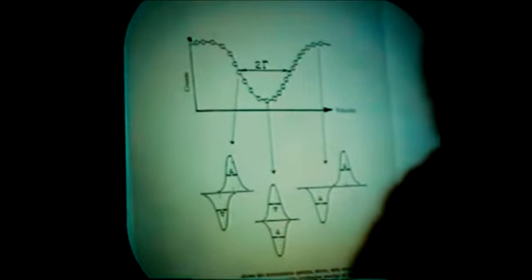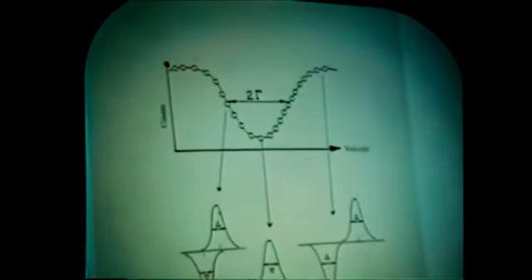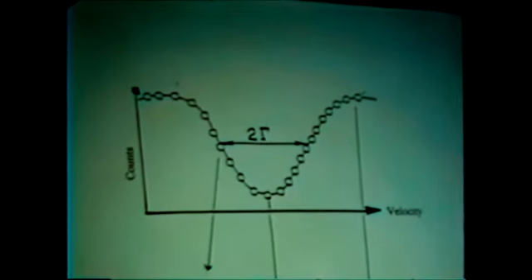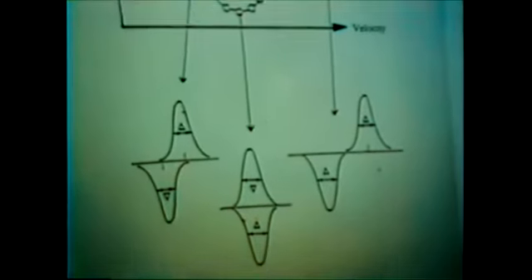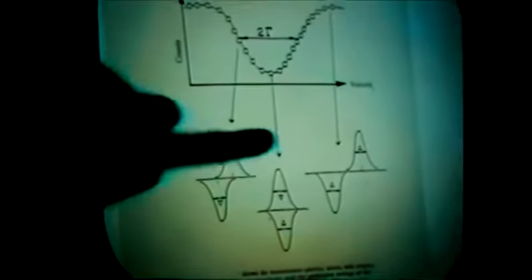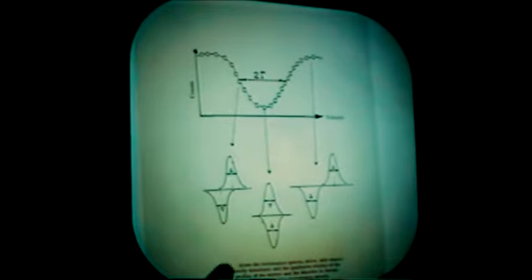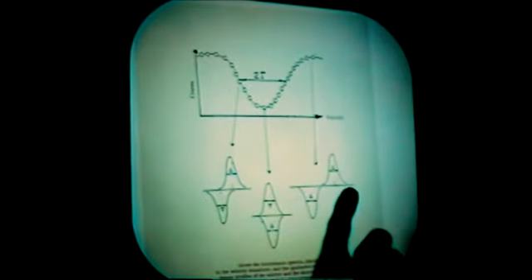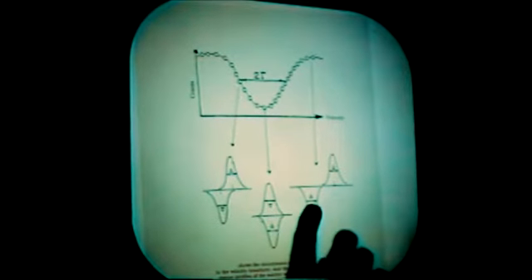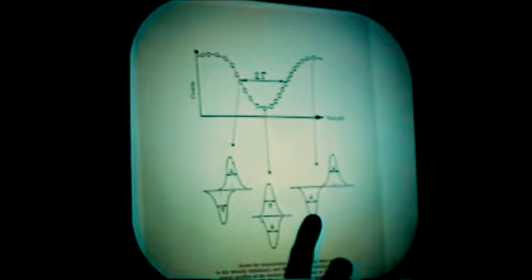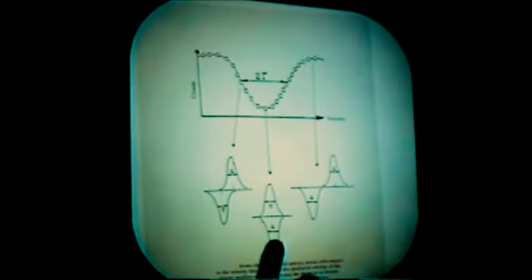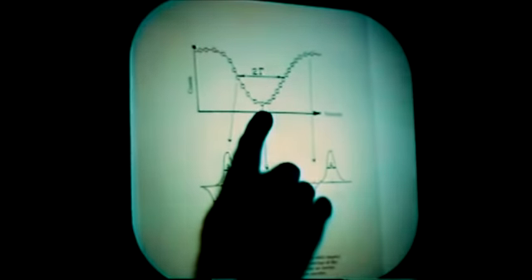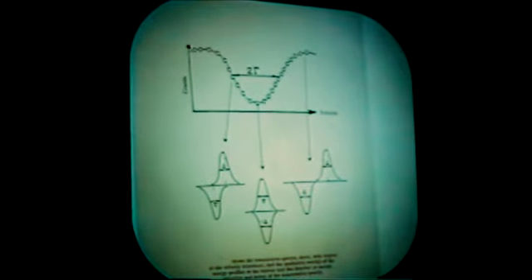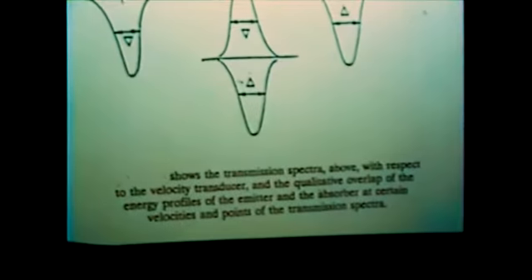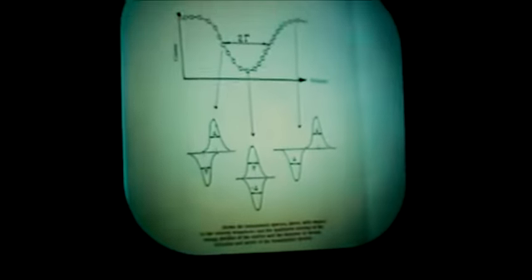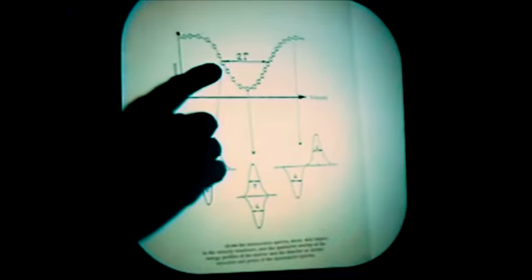Now this is what the transducer does. Let's say this is the energy of the excited state that you're trying to excite. At this velocity, you're moving this in this way, so you have no match between the energy of the photon and the state you're trying to excite. As you move in, when you have maximum match, then the number of counts, of course, goes down because you have resonant absorption. You're matching the state you're trying to excite with the energy of the photon. Now, if you go further, then the overlap will be less, and the number of counts will be less.